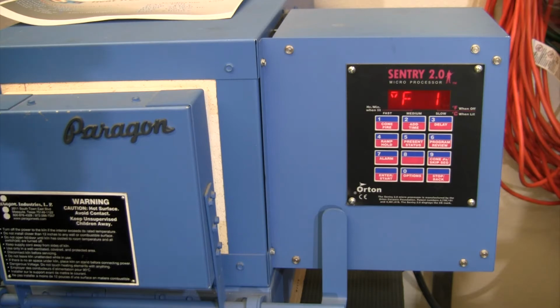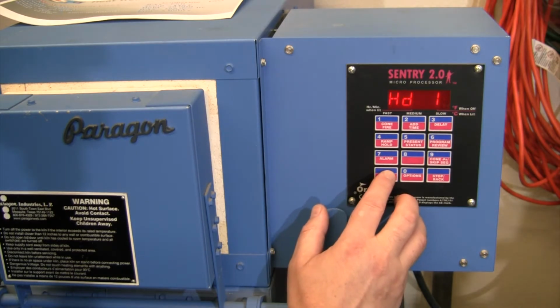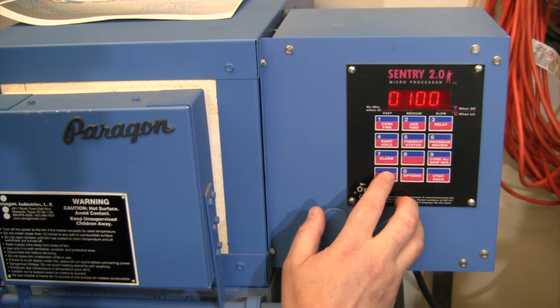And again, because it's ramping up full speed, the kiln's cold. It's actually going to blow past. When it would warm up, it would get up to probably about 360. That's why we're going to hold that there for 20 minutes, stabilize the kiln. Ramp number 2, we're going to do 100 degrees per hour instead of full, so only 100 degrees per hour is how quickly it's going to warm up.